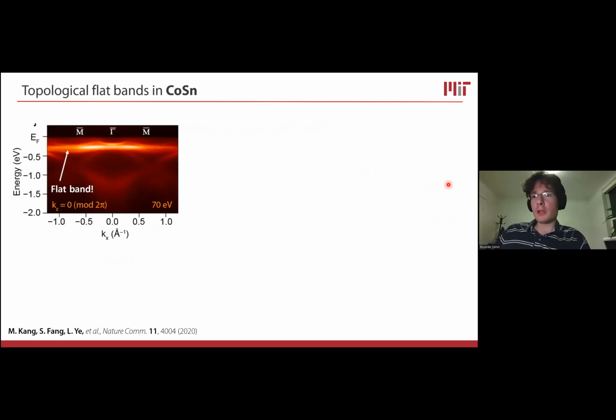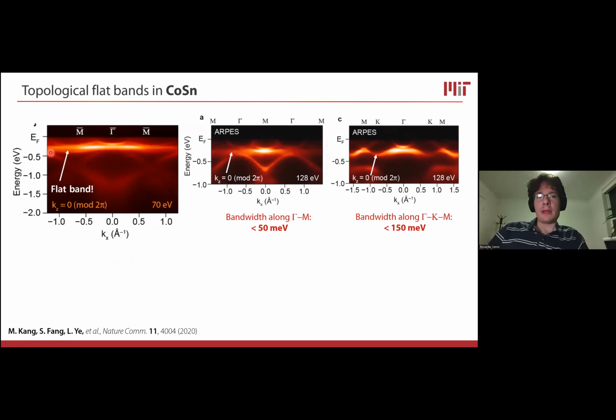And so lo and behold, what we saw was these beautiful flat bands in cobalt tin, which is really flat in all directions in momentum space. It acquires a little bit of a dispersion along the gamma to K direction, and that's due predominantly to next nearest neighbor hopping, which makes the bands not perfectly flat anymore, but it gives them a little bit of a bandwidth. But compared to the dispersion of the Dirac bands, which is of order 2 electron volts, these bands are really flat, and they are meeting the Dirac bands exactly where they're supposed to at the gamma point.